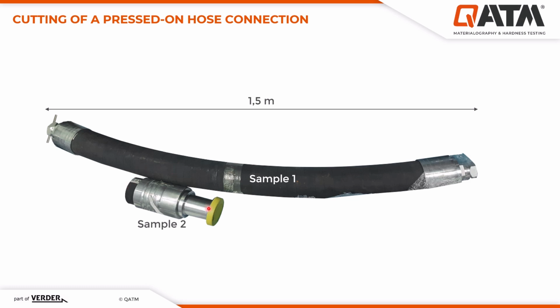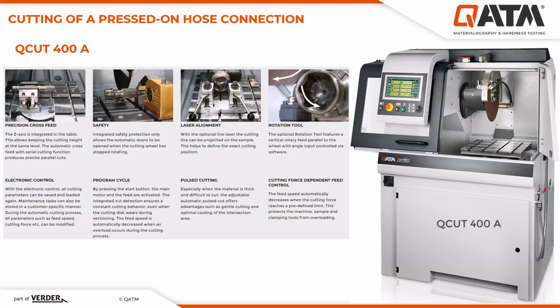And on the second sample, the challenge is also the combination of rubber and metal. When you cut the sample longitudinally, the different parts of the sample, of different size, come together and try to stop the cutoff wheel, and then you can also break your cutoff wheel. Now I want to show you how, with the appropriate parameters, you can have the best results.